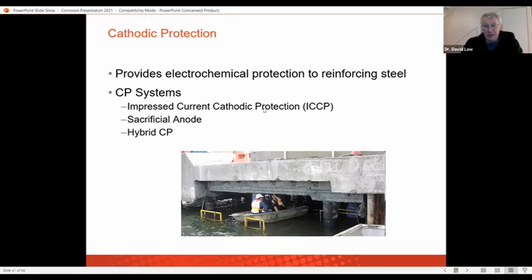There is the impressed current cathodic protection that uses an electrical current to protect them. These are the ones that are most used. These are the ones that have been running now for 30, 40 years. And these are the ones that we've been studying to see, as they're reaching the end of their design lives, are we seeing protection left on the structure by the action of this cathodic protection over that long period of time? Because if it is, it means that those structures will last longer, and so we don't need to reinstall ICCP, and they may well reach their design lives. And trying to understand that in the different locations, the different elements, is very important now. There's a lot of these systems that are at the end of the design lives.